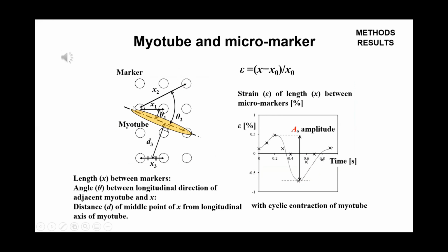The distance between markers X is traced at the microscopic movie image during cyclic contraction of myotubes. The amplitude A was measured by the difference between the maximum value and the minimum value of the cyclic variation of X. The tracings are analyzed with several parameters: angle theta between X and the longitudinal direction of the myotube, and the distance d from the contracting myotube.